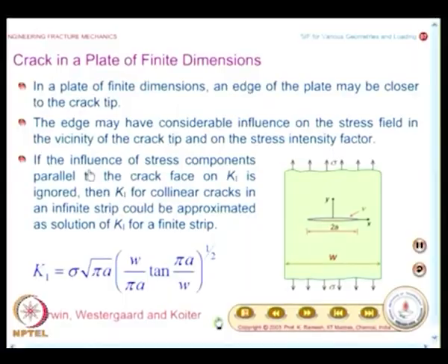And I would like to emphasize again, the influence of stress components parallel to the crack face on K1 is ignored. This is the kind of approximation that we make. And this all happened at a time when people had only a slide rule for calculation, they did not have a computer.